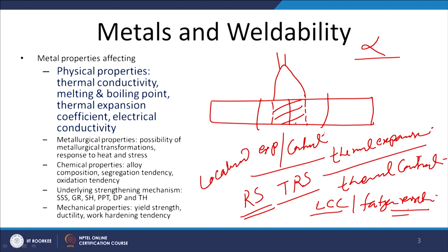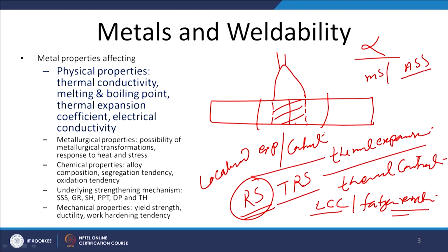So, all those metals which offer a higher thermal expansion coefficient during the welding will show greater residual stresses, greater distortion tendency, and reduced fatigue resistance as compared to metals which offer lower thermal expansion, because the magnitude of the thermal expansion and contraction due to the weld thermal cycle will be limited in case of low thermal expansion metal systems as compared to high thermal expansion coefficient metal systems. For example, if we compare mild steel and austenitic stainless steel, ASS offers a higher thermal expansion coefficient as compared to mild steel. So, there are more issues related to residual stress and distortion as compared to mild steel, in case of the welding of these two metal systems by the fusion welding process.